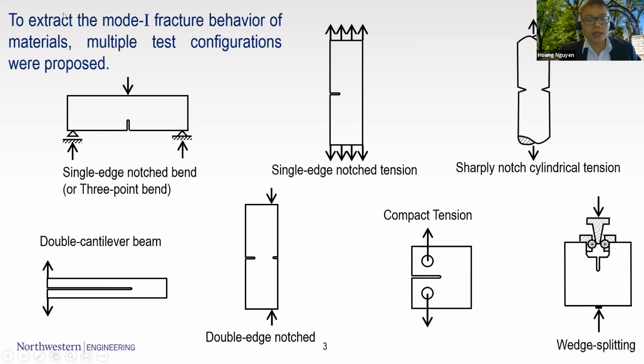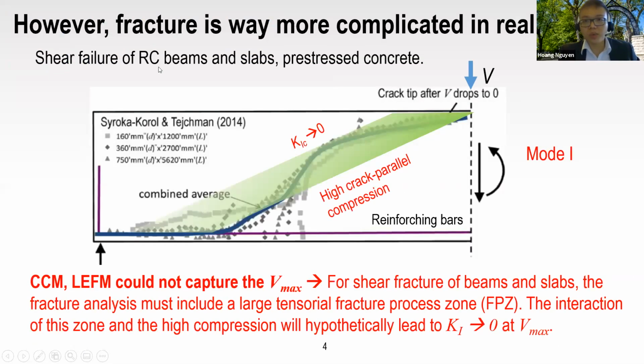So for the opening mode, to extract the fracture behavior, there are multiple test configurations. You can use the single edge notch bend test, which is similar to the 3-point bending test, or you can use the same type of specimen, but put it in tension. Another type is the sharply notched cylindrical tension and the double cantilever beam. In some extended creep experiments, people use double edge notch, and a lot of composite testing involves the compact tension. And Tschegg, around 1985, came up with wedge splitting tests, which are another way to create tension ahead of the crack tip and trigger the opening mode. However, fracture is way more complicated than that.